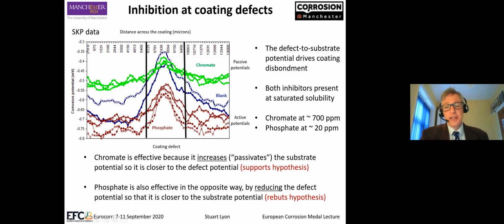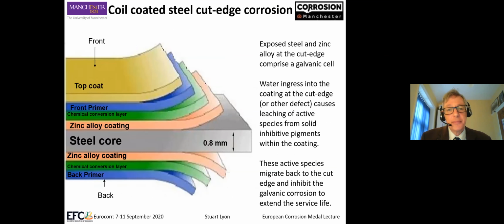So chromate is effective because it increases the substrate potential, so it's close to the defect potential, which is in support of that hypothesis. Phosphate is also effective, but in the opposite way. It reduces the defect potential, so it's closer to the substrate potential, which goes against the hypothesis. So that hypothesis is sometimes right and sometimes wrong, which means it's not a universal idea. So that was one of the first things we did with paint.